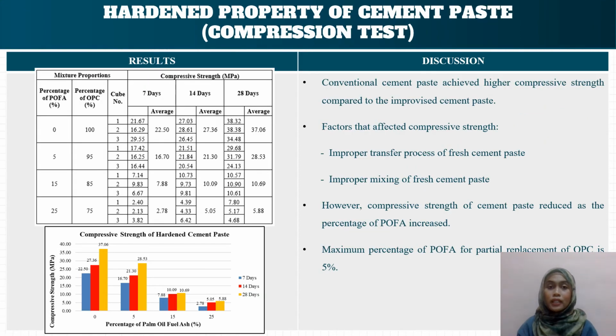Next, to determine the hardened property of cement paste, a compression test was done. From the result shown in the slides, it can be seen that the conventional cement paste has achieved a higher compressive strength as compared to the improvised cement paste. The strength of the cement paste will be decreased due to several factors such as the improper transfer process of fresh cement paste from the mixing bowl to the mold, and the improper mixing of fresh cement paste.